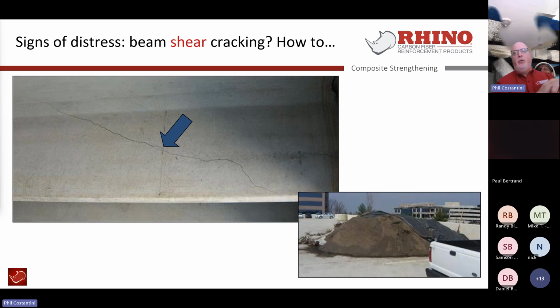Yeah, so no need for that. It was less than a 1/16 of an inch crack. But the concern there was we didn't need to shore post it. Obviously the contractor didn't abruptly leave that load of soil there. He had to get it off of there. So the added vibrational equipment that he used and everything else opened up cracks on the other side as well, but it didn't show any displacement. So the good news is we were able to chemically inject it with epoxy.